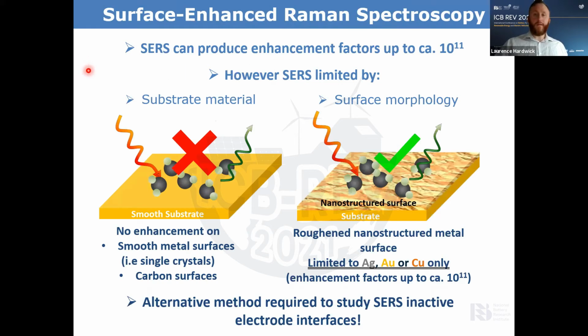So what we're interested in doing is to use surface enhanced Raman spectroscopy, and this can produce enhancement factors up to 10 to the 11. So we have a plasmonic substrate which enhances the Raman signal, and this is usually limited to gold or silver electrodes with a nanoscale roughness, where we can detect these species. But this limit says gold or silver, or maybe even copper.